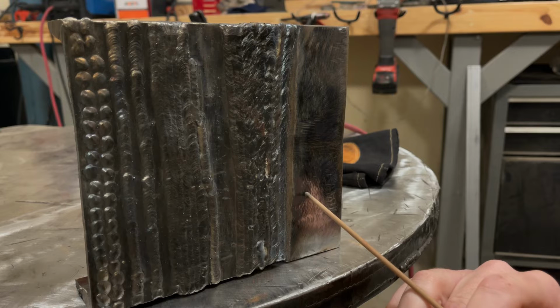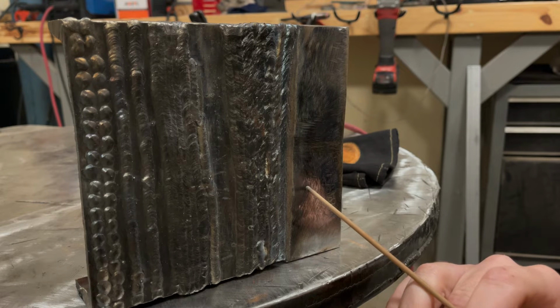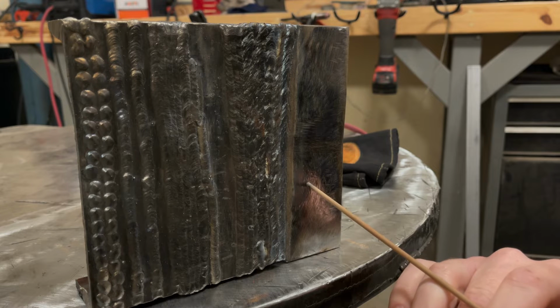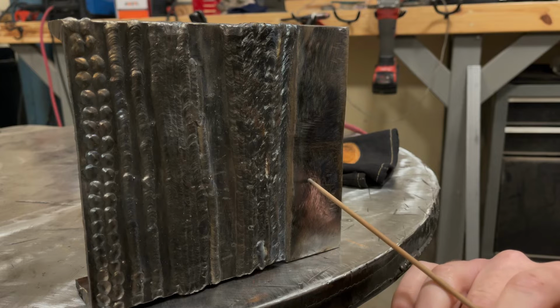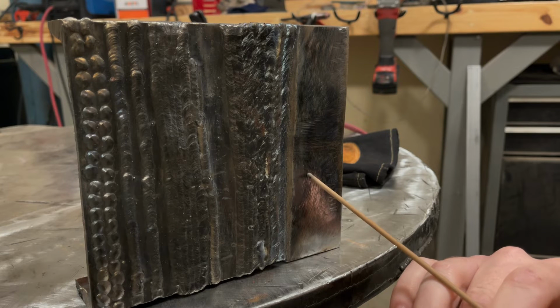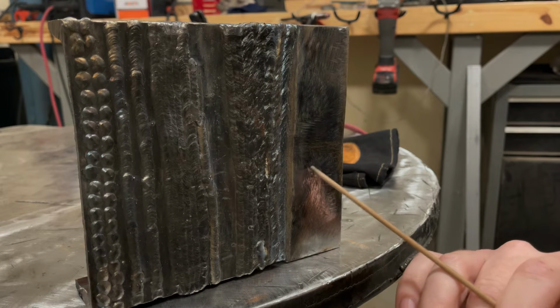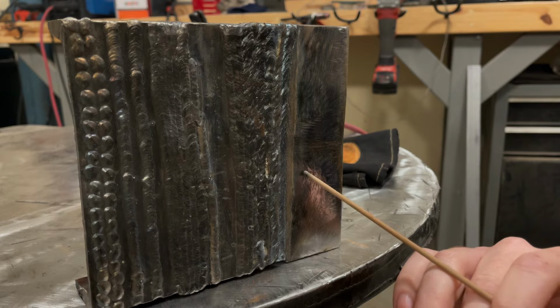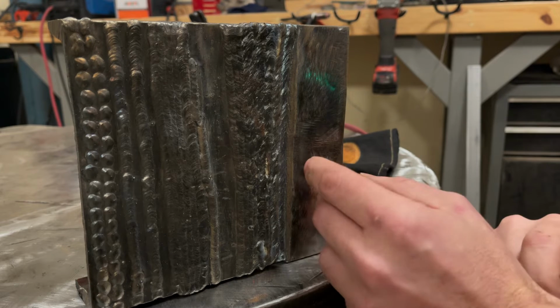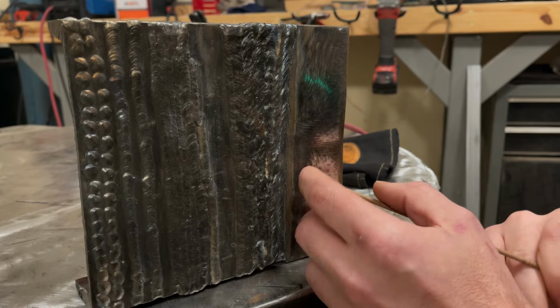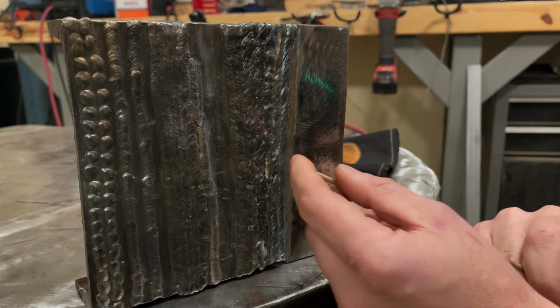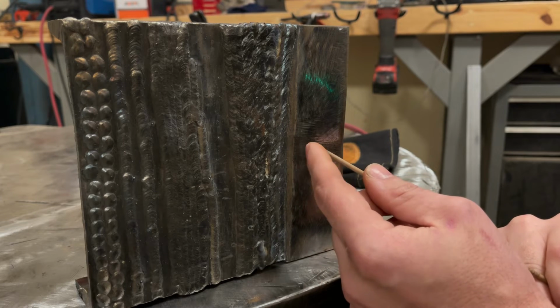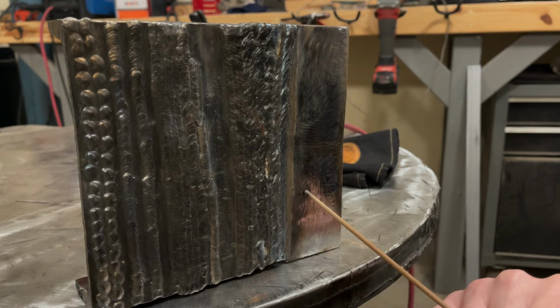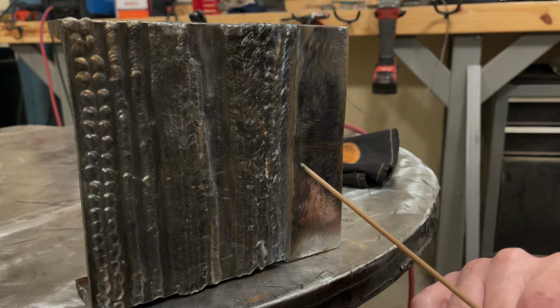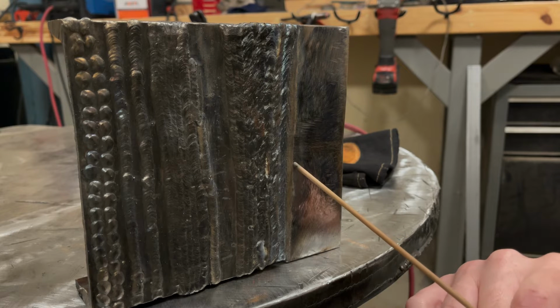You're also going to want to, I hate to say it, but cram the rod into the puddle. Now obviously if you cram it too much into the molten puddle, you're going to have the rod stick and you don't want that. But you want to keep some pressure to where you're about as far in as you can get. One of the things you have to understand is, especially with 6013, it has a very bad tendency where the flux on the tip of the rod doesn't melt off fast enough in the internal core. The metal rod inside of this ends up burning back further than the edge of the flux, and it essentially extends your arc gap longer than you think it is. So if you don't keep some pressure on the flux in the molten puddle, it's not going to eat that flux away and keep your arc gap short.